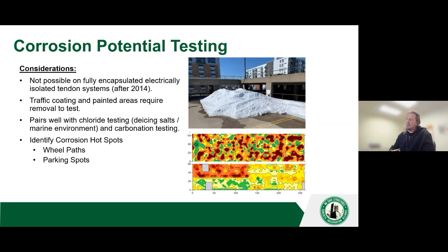When we do that test, we want to do a full survey of an area that we're concerned with, and we want to see what's the higher likelihood versus the lower likelihood of active corrosion going on. This is not going to be possible with fully encapsulated isolated tendons. If it's got a heavy traffic coating or the bottom soffit is painted, we can still do this test. Oftentimes we're going to have to damage the coating a little bit so that our reference electrode can take the readings. This does pair well with chloride testing, especially in areas where they're using de-icing salts or a marine environment.